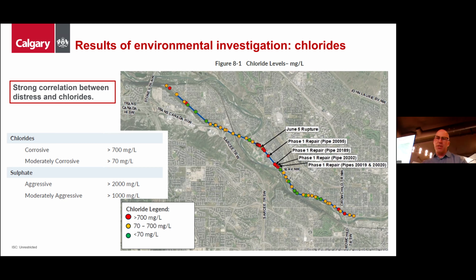But back to the topic here. So we obtained the soil samples on the 5 additional repair sites, and that information, along with soil samples obtained back in 2014 and in 2024, is illustrated here on the slide. You can see that there are low, moderate, and high levels of chlorides along the entire length of the feeder main. And it's noteworthy that none of these samples showed any sign of aggressive sulfate levels, which is actually something that we would find more typical in Calgary's elevated sulfates in our soils and not elevated chlorides.